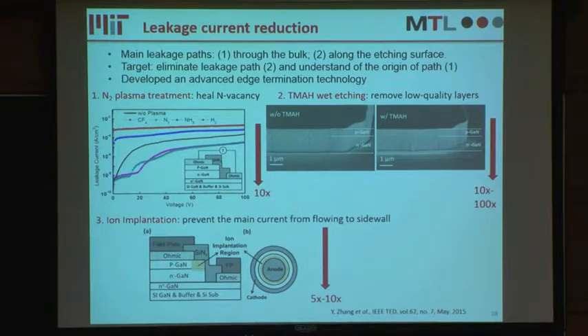If we combine all 3 of these technologies, we can lower the leakage current by 2 to 3 orders of magnitude, and we identify there is no leakage path along the etching sidewall.